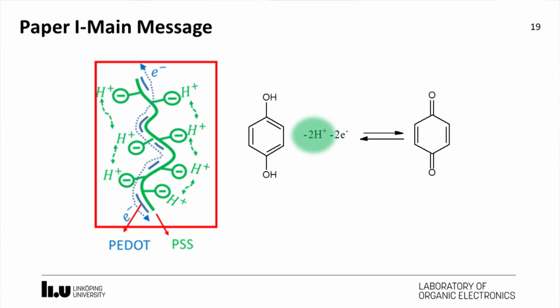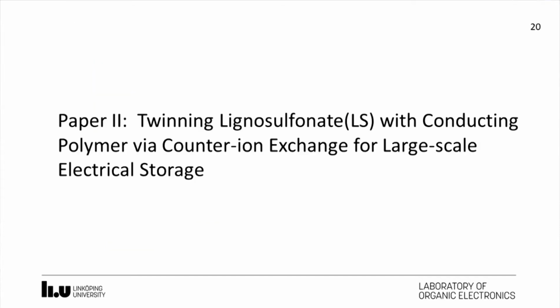So in this paper, we found that for these two proton-coupled electron transfer reactions, proton transport is the rate-determining step, and that makes PEDOT:PSS an excellent electrode material due to the efficient proton conduction in the PSS. In the second paper, we studied the adsorption of lignosulfonate onto conducting polymers and the mechanisms, as well as large-scale application.